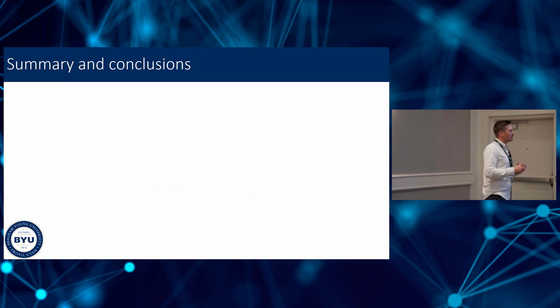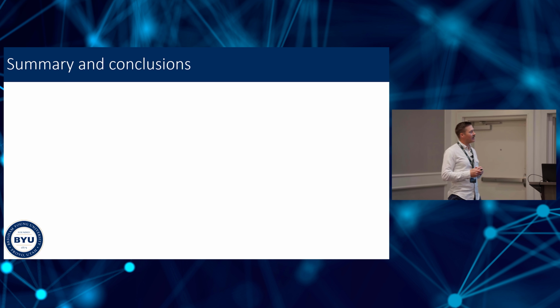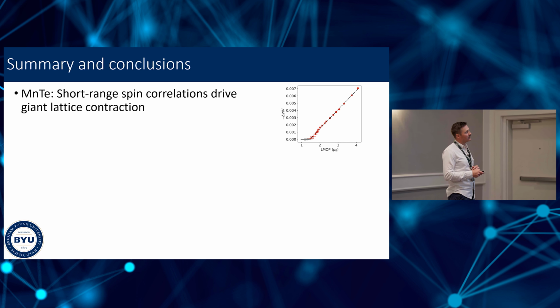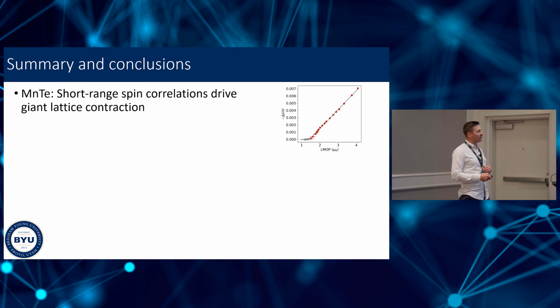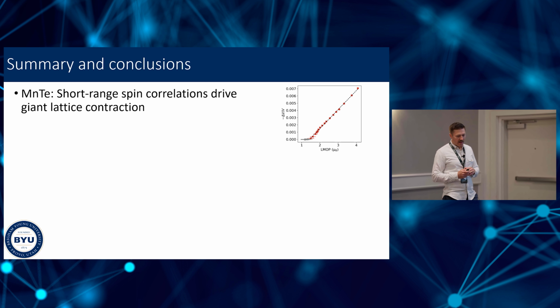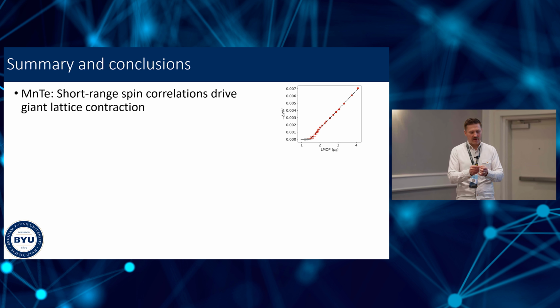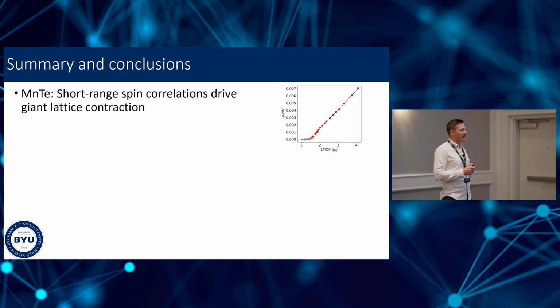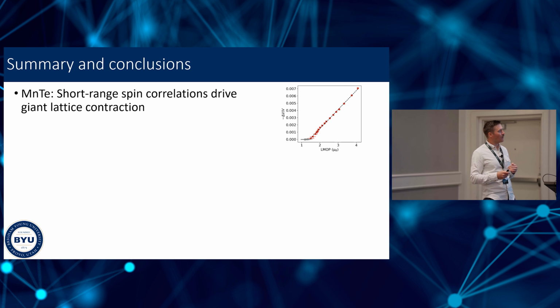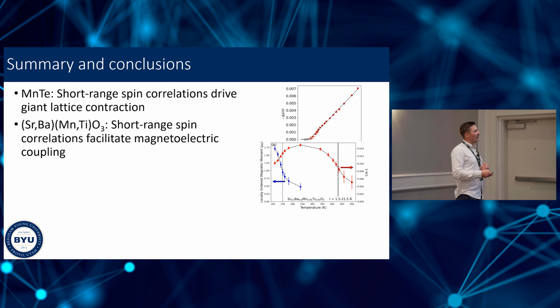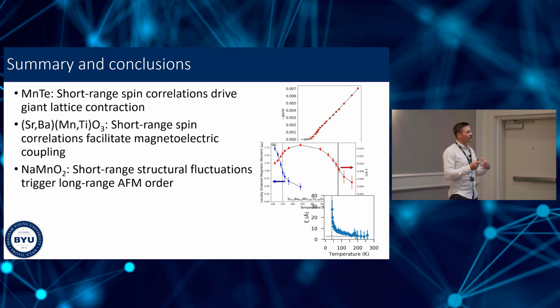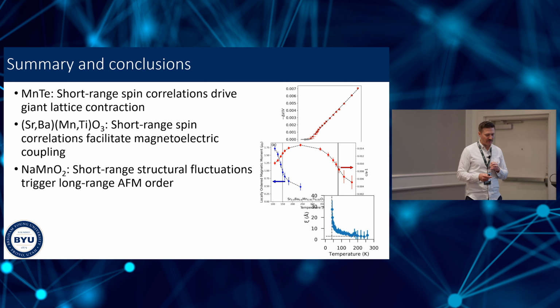So let me wrap up here. We've looked at 3 different examples. We've looked at manganese telluride, where short-range spin correlations drive a giant lattice contraction, and that giant lattice contraction proceeds uninhibited by the transition into the paramagnetic state. It just continues its merry way along. It doesn't care what the long-range order is, just what the local magnetic correlations are. We saw in strontium barium manganese titanium oxide, once again, that short-range spin correlations can facilitate magnetoelectric coupling in a multiferroic material. And then in sodium manganese oxide, short-range structural fluctuations trigger long-range antiferromagnetic order.